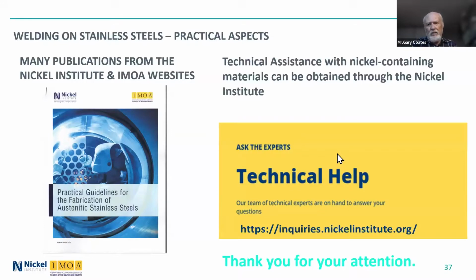It does add strength to the stainless steel. It's one of the reasons why the dual grade 316L is the standard material. They tend to have a slightly higher nitrogen content because the nitrogen makes sure that the alloy is as strong as the minimum requirement for the 316 material while having a low carbon content. There are some nitrogen alloys like 316LN, which have even slightly higher nitrogen content, 0.12 or 0.14%, and they do make it stronger.